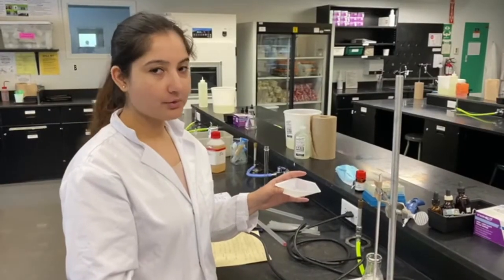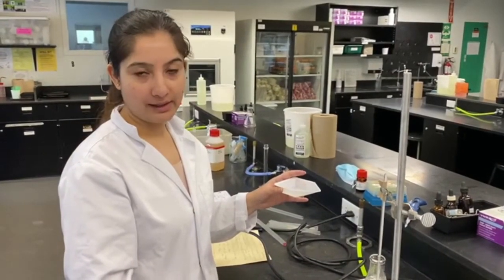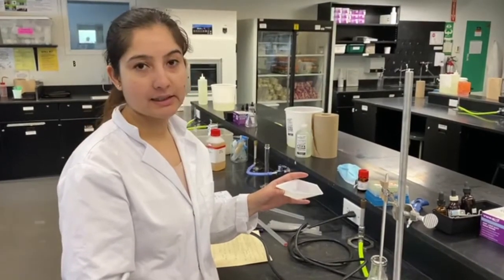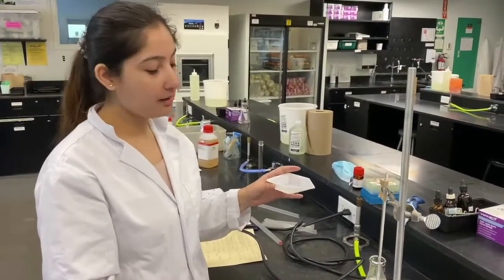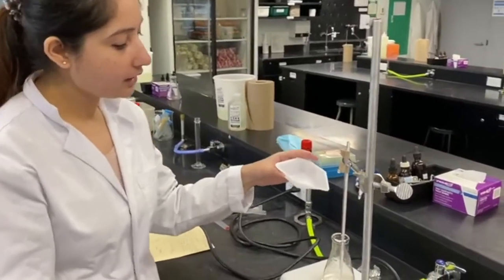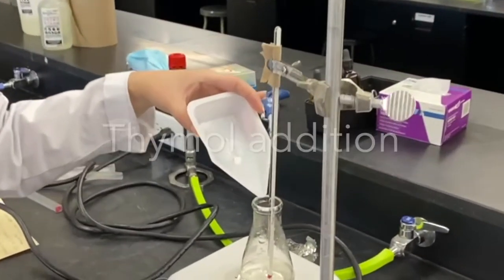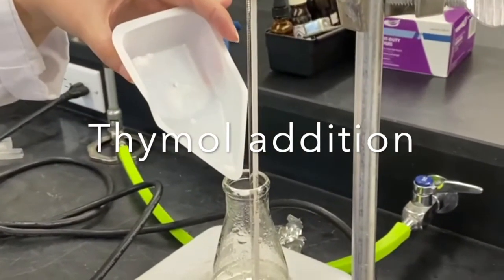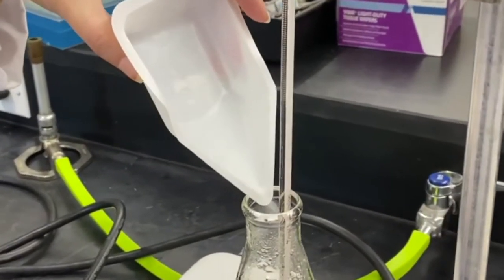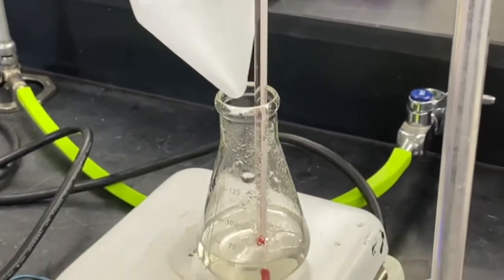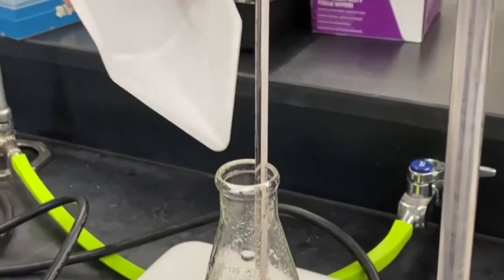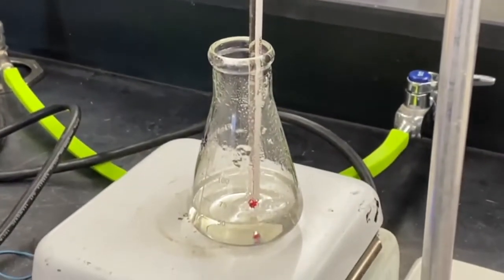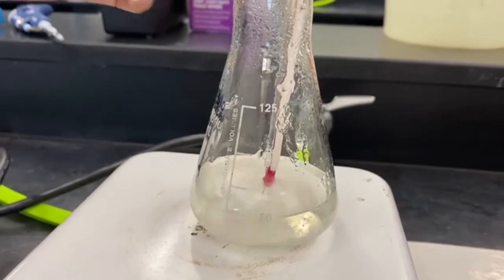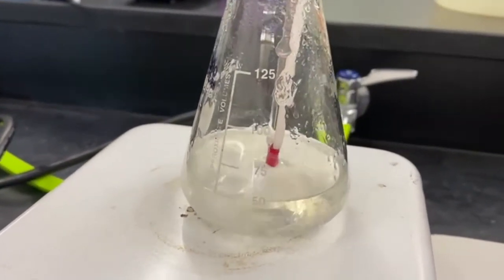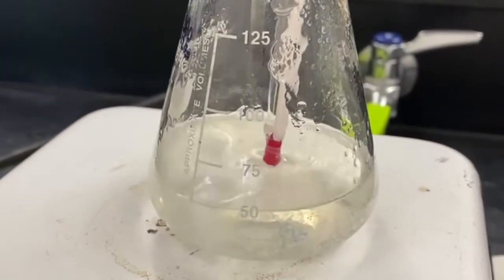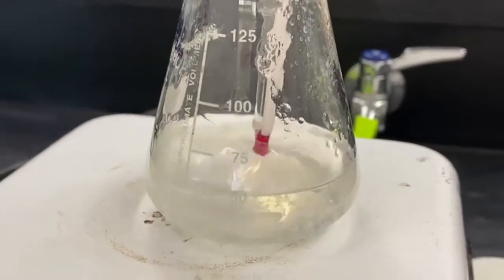So to the solution of chitosan and Tween 80, which we produced by heating it at 60 degrees Celsius for 1 hour, we'll be adding thymol here. And we'll be mixing it so that thymol will act as an antimicrobial agent here. So we just added a stirring rod here to mix thymol properly with the chitosan and Tween 80 solution, and we'll keep it for the next 20 minutes to mix it up.